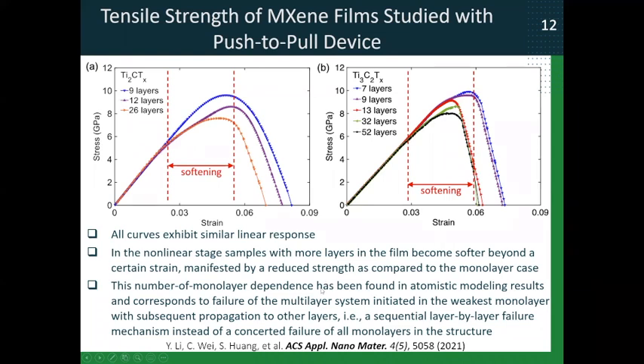So we started to look into how these stacks of monolayers fail and why they demonstrate this behavior. And again, we found out that the failure mechanism is basically a layer by layer failure instead of a concerted failure of all monolayers in the structure at once. And this was a reason why instead of sharp degradation of sample here, it just becomes softer, but still can maintain mechanical load.